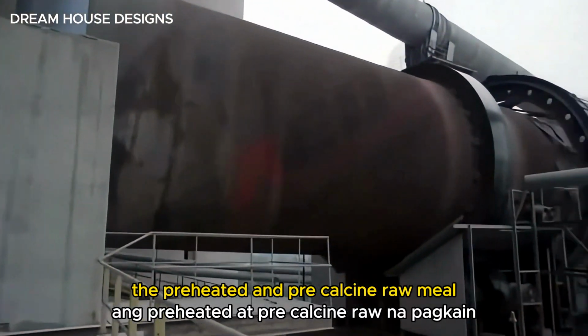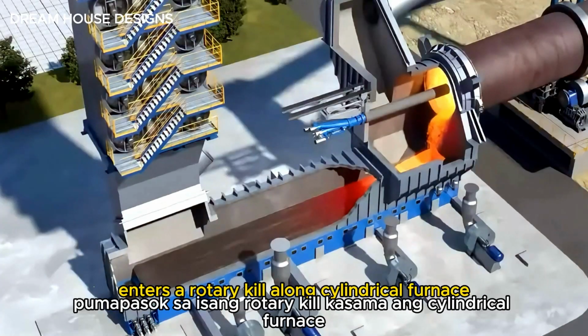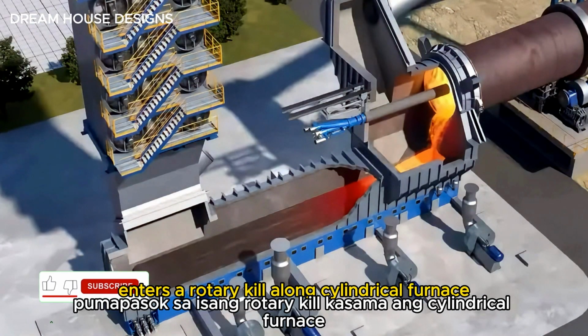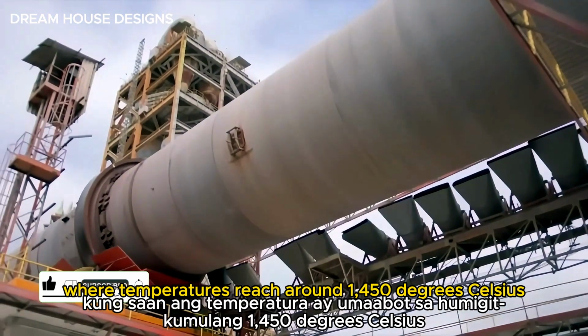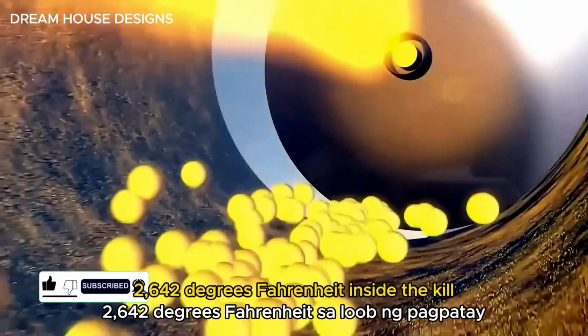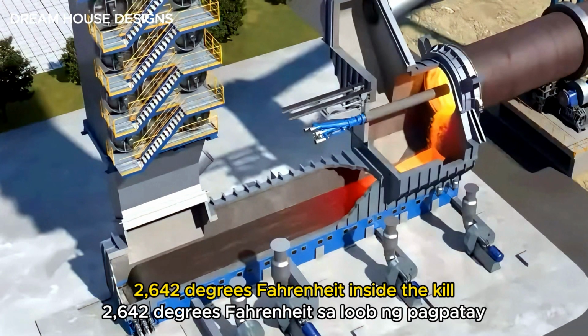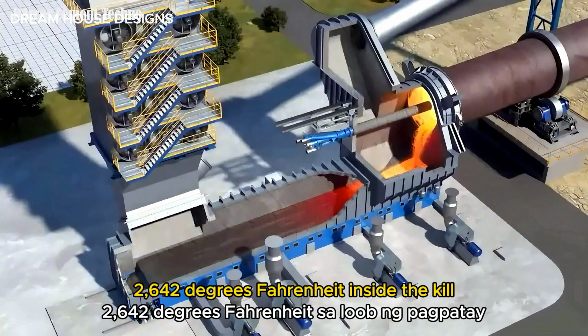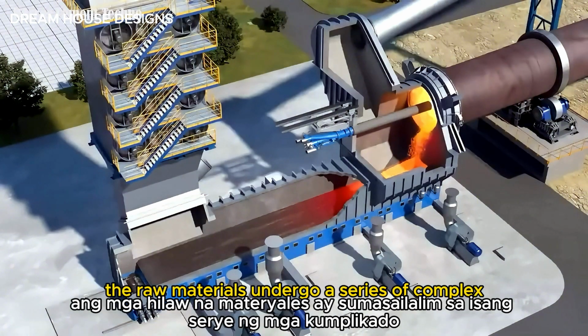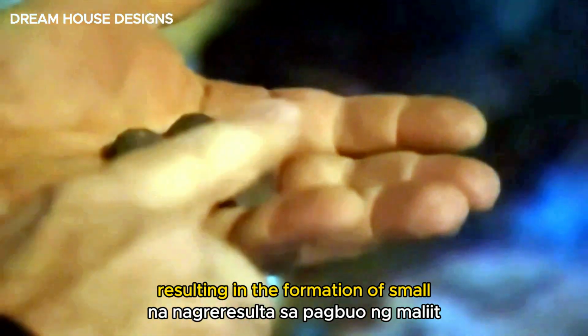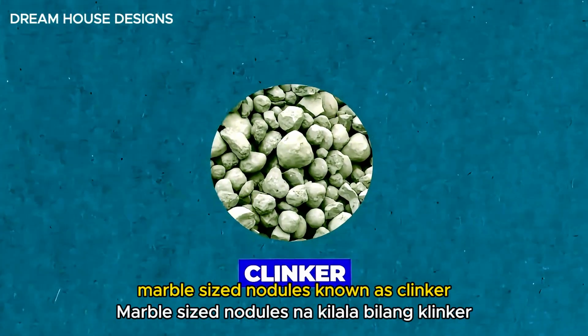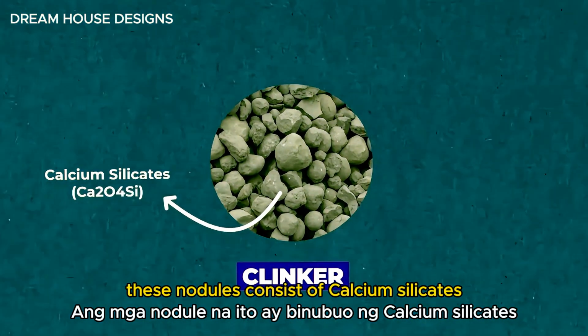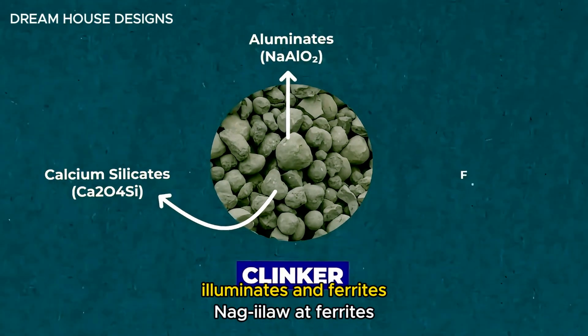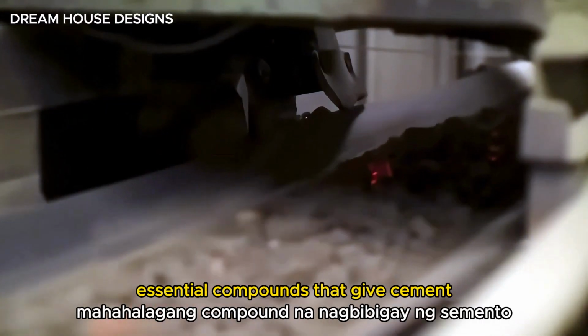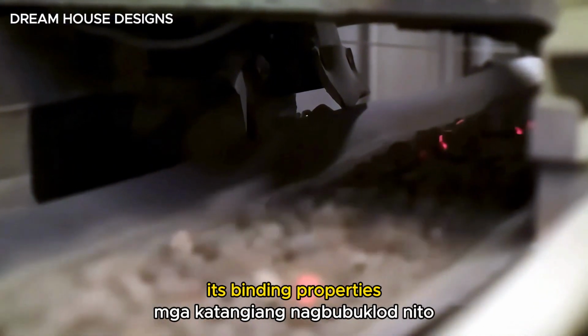The preheated and precalcined raw meal enters a rotary kiln, a long cylindrical furnace where temperatures reach around 1,450 degrees Celsius to 2,642 degrees Fahrenheit. Inside the kiln, the raw materials undergo a series of complex chemical reactions and sintering processes, resulting in the formation of small, marble-sized nodules known as clinker. These nodules consist of calcium silicates, aluminates, and ferrites, essential compounds that give cement its binding properties.